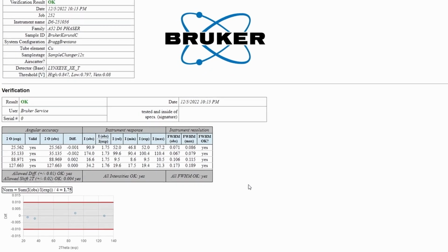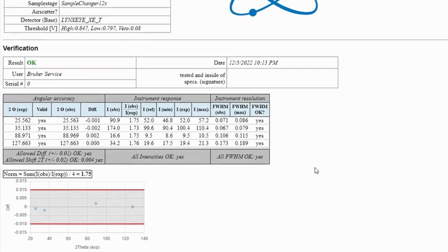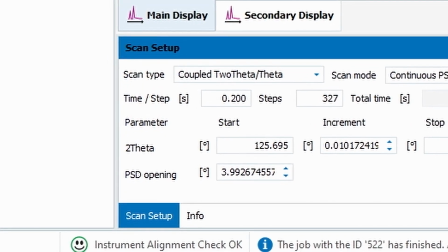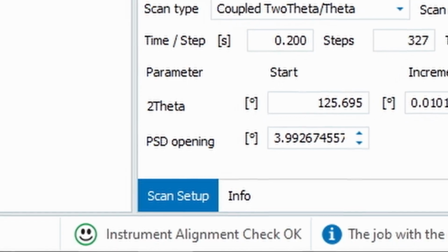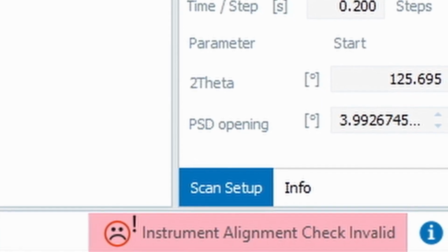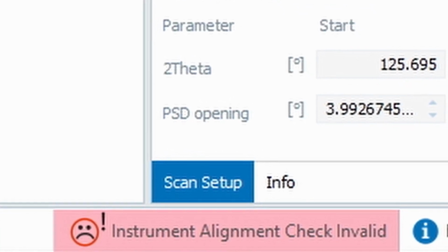Depending on the features available on the stage and the tube anode material, this verification may include the peak position, relative intensity, and full width at half maximum of 4 peaks across the measurement range. This will result in the generation of a report showing the calculated value and an easy to identify icon: a green smiley indicating the system is ready to use, or a red frown if the system needs new reference values. If the red frown is shown, simply press the referencing and verification button.